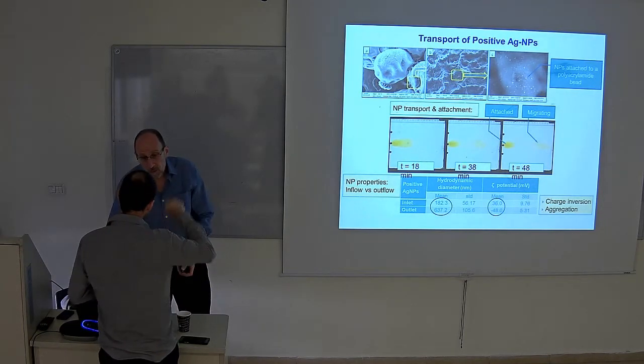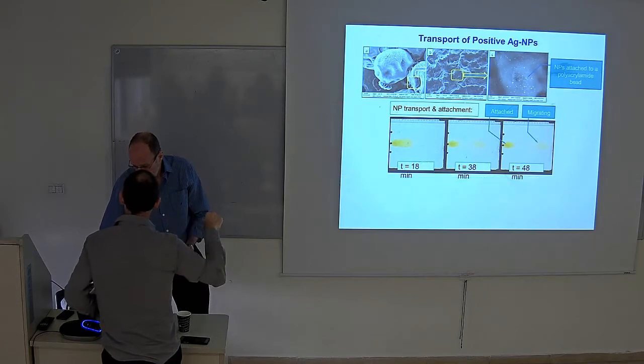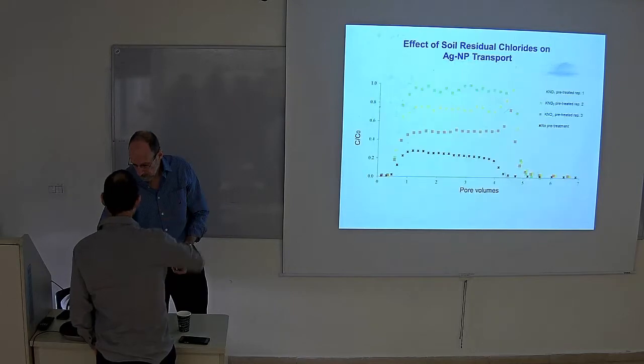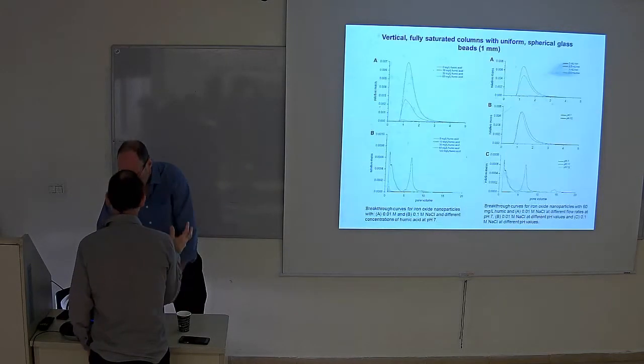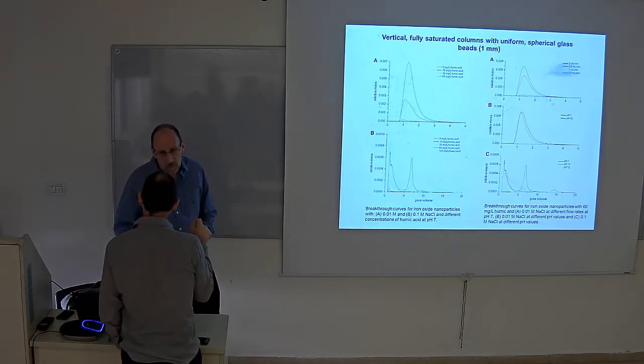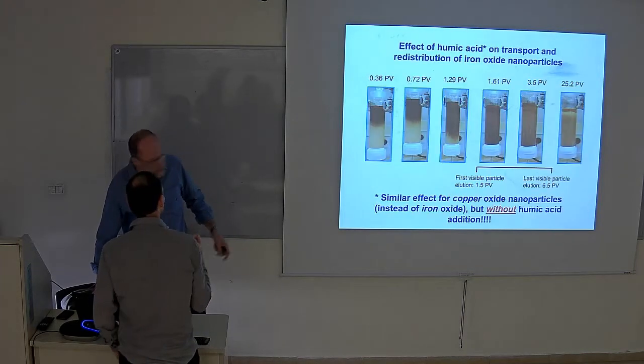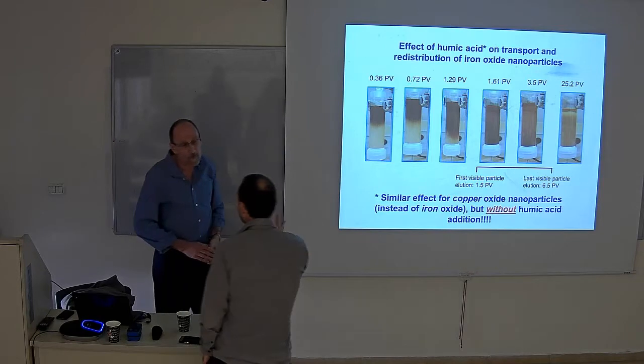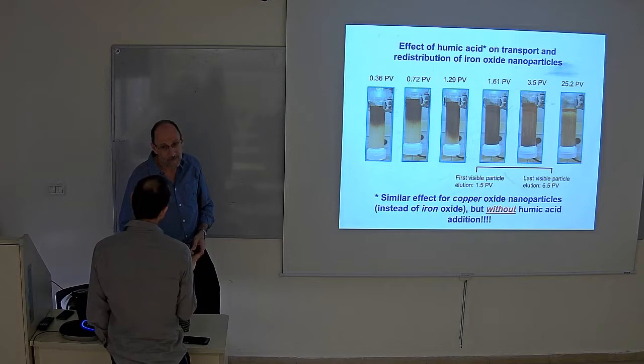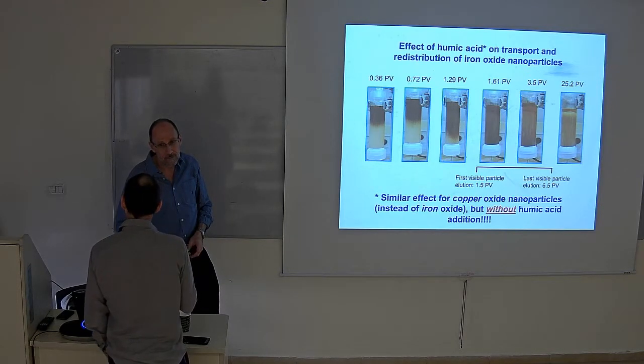Those two pulses, those two peaks, the twin peaks that you see during the breakthrough of particles. You said that it's because it's clogging and then releasing. Do you see the pressure fluctuations as well? We didn't. It would be interesting if it correlates, because if that's the mechanism, then you would expect there to be measurable changes in pressure. That's the question.